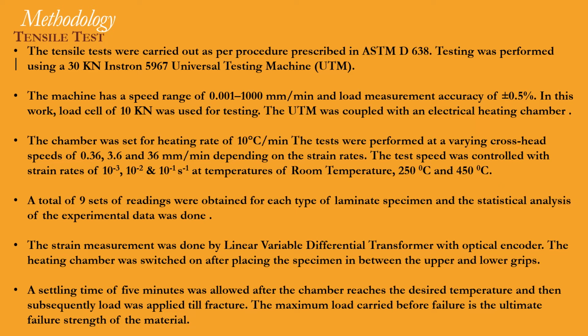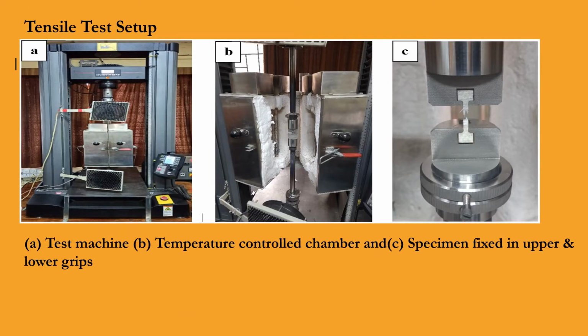The heating chamber was switched on after placing the specimen in between the upper and lower grips. A settling time of 5 minutes was allowed after the chamber reaches the desired temperature. Then subsequently load was applied till fracture. The maximum load carried before failure is the ultimate failure strength of the material. Tensile test setup. The figure shows the tensile test setup. Figure A shows test machine, B shows temperature controlled chamber, and C shows specimen fixed in upper and lower grips.